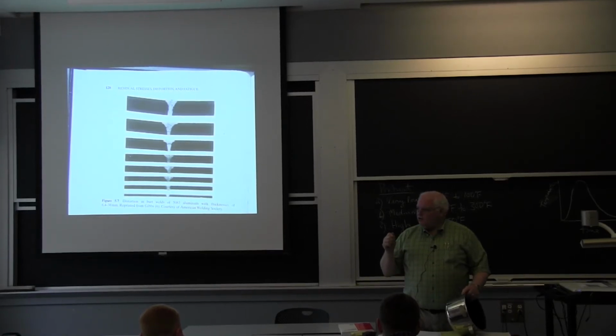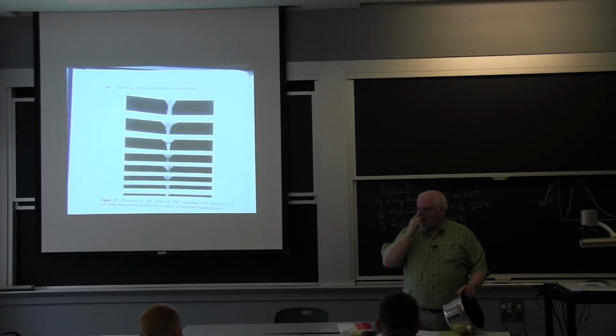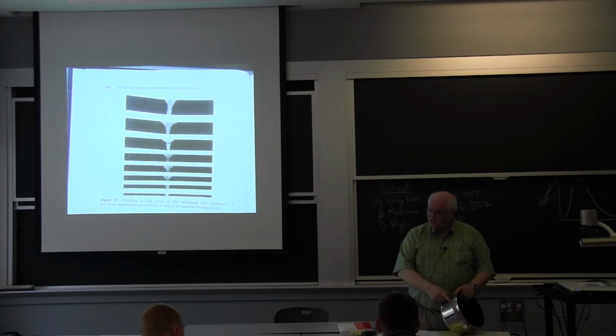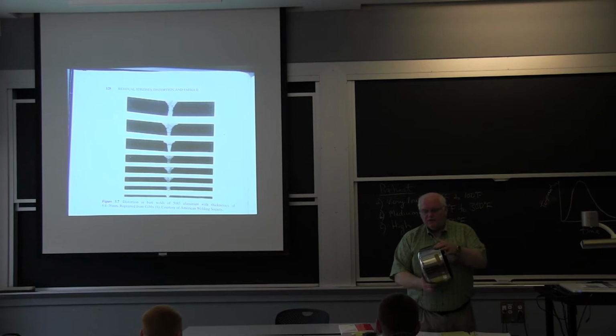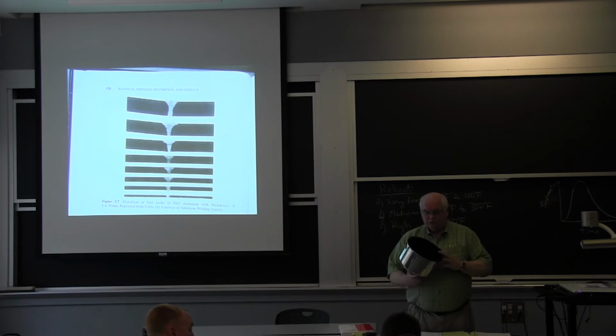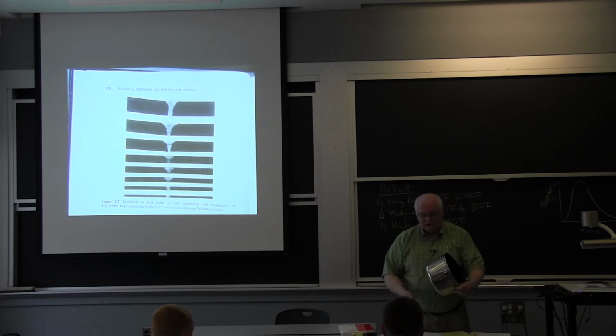Told me the cracks weren't showing up until they showed up in Japan. So they'd ship them out of Brooklyn, and by the time they got to Japan, they had cracks. So they brought these. Actually, some of the cracks have extended over time, or they did for the first few months after they brought it to me. But there's cracks in here. You can look on the inside, and you can see them. See light through there. Okay.